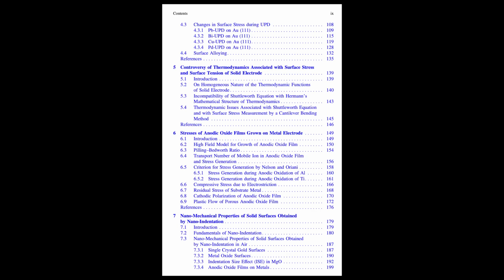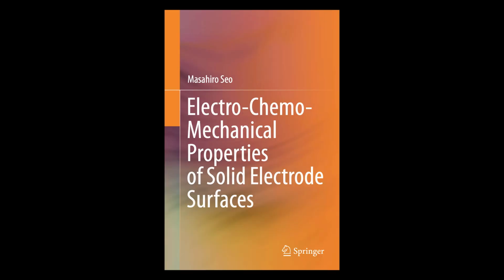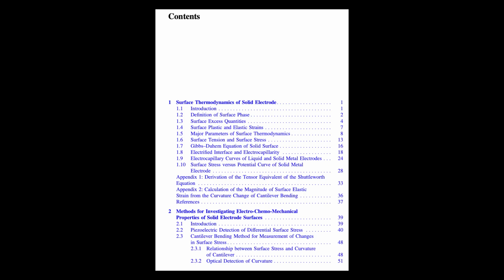You really can't. And then finally, if we want to see how surface stress changes over time, researchers use something called dynamic stress analysis, often paired with electrochemical impedance spectroscopy, or EIS. Okay, what does that involve? Basically, you apply a small oscillating electrical potential to the electrode, and you analyze the resulting wiggles, the oscillations in both the electrical current and the surface stress. Right. By looking at how the stress response relates to the potential input, things like amplitude and phase shift, you can get insights into the kinetics, the speed of the processes affecting surface stress. So we're not just taking static snapshots, but watching how these forces evolve in real time as we tweak the electrical conditions. Okay, that gives us a really good handle on how these invisible forces are actually measured.